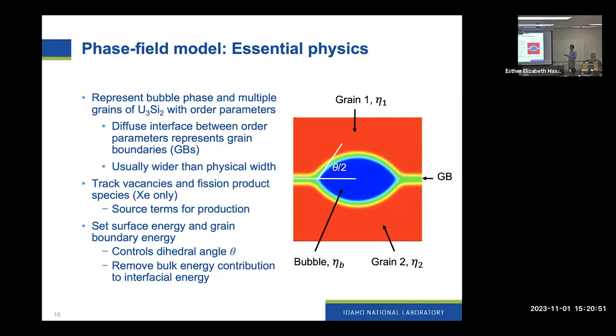For this particular flavor of phase field model, we also track the local defect concentrations in the form of the local vacancies and fission product species. So, principally, xenon is the most prevalent of those fission product species. There is some krypton in there, but we have assumed that we can represent the physical properties well enough with xenon. So we have source terms for the production of those defect species. And then we also need to get the geometry of these bubbles right, so we need to set the surface energy and the grain boundary energy, because the balance of those two controls the dihedral angle, which was shown to be an important parameter in the Bison model.